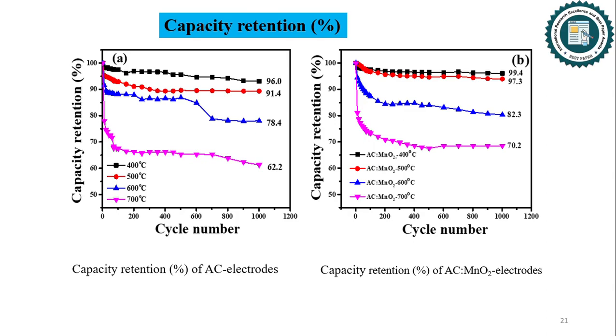So here we can see that AC 400 degrees centigrade electrode demonstrated wonderful stability of 96%. Whereas hybrid composite electrodes, particularly AC MnO2 400 degrees centigrade, demonstrated remarkable 99.4% of initial capacitance after 1000 cycles, attributed to MnO2's pseudocapacitive behavior and redox reactions, mitigating material degradation during cycling.